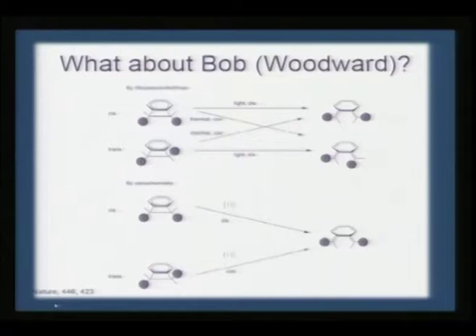And what about Woodward-Hoffmann reaction conversion, say for the cis form converting to this product and the trans form converting to this product. These are stereospecific conversions, and whether you use light or heat, the conversions are very selective. For example, the conversion of this cis isomer to this product is very selective only if you use a thermal reaction, whereas if you use a photoinduced reaction it converts to this, so it is very selective that way. Similarly for the trans one. But if you use sonochemistry, the cis or the trans will give only one stereospecific product. So this is not only selective for free radical mechanism, you also see that you can get stereospecific products by using sonochemistry.